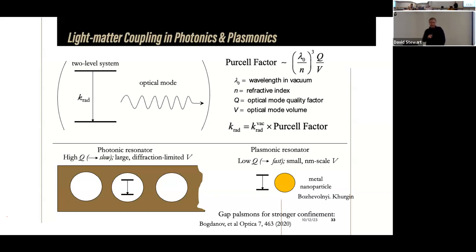That's actually very interesting. But anyway, what he proposed is that if you have, let's say, a qubit atom, which is much smaller than the wavelength, but you place it in a cavity, in this case a dielectric cavity, then since light goes many times between mirrors, effectively coupling increases. And the increase in coupling is proportional to the quality factor of this cavity, not surprisingly. The higher the Q, the more times it would travel between mirrors, and inversely proportional to the volume of your cavity.